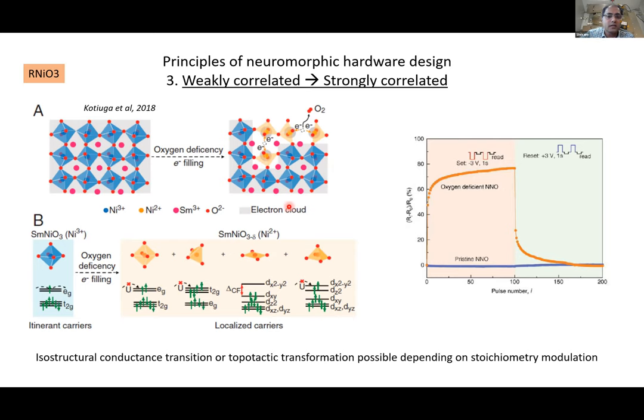In addition, if you're interested in exploring the electronic effects of defects beyond the dilute limit, you can actually reconstruct the crystal field splitting by introducing extensive defects. So you can go from perovskite to other derivative phases, Brownmillerite is one example. So you can have even structural distortions and reconstructions in addition to electronic reconstructions. So you can create a range of metastable compounds, and you could in principle go between two structures or just explore the properties of intermediate metastable phases.